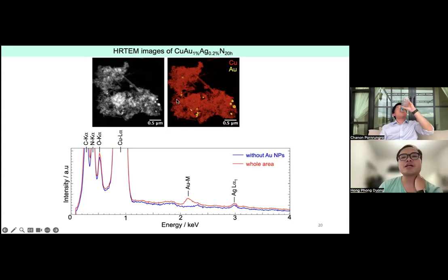We employed HRTEM and we found that the presence of gold was like nanoparticles in the material. It looked like this, and even by EDX we found that gold was kind of localized. On the other hand, silver was more homogeneous on the whole material surface. This is the TEM.